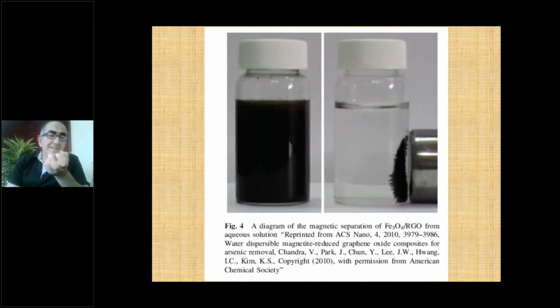This is another similar slide about how we can do these processes by using external magnets. But this is a good figure for me, because at the left you can see the adsorbent which adsorbs your analytes in the solution, but it was dark because it contains all the adsorbents. Then after separation, at the right, we use a magnet. Then all the adsorbents, including our analytes adsorbed on the surface of the adsorbent, we can easily collect on the surface of the vial, and you can easily see the clear solution. At the beginning, a very dark solution. At the end, a very clear solution. It means that the separation is very successful.